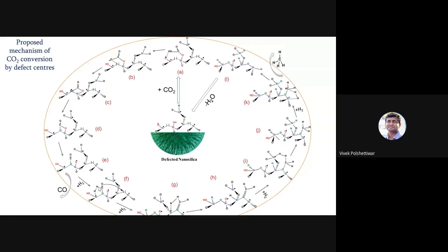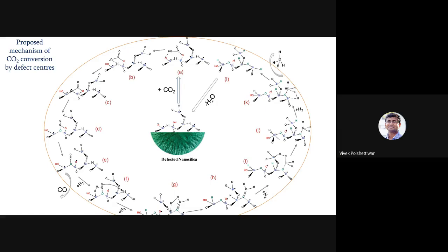You see here, Si radical, it dissociates the H2 into H, and another H goes to this carbonyl to form this p-carbonyl species. I'm skipping the detailed mechanism, but this is how we propose the mechanism based on the in situ IR studies. Okay, so that was the example where we created a sand to nano sand, ideally a silica to nano silica, and then created a defect by taking out some oxygen from that SiO2 to make it catalytically